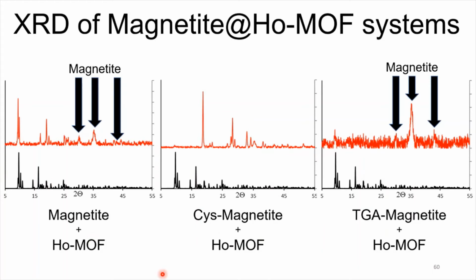Now, in the case of cysteine, it's a work in progress. We're still not sure what happened, but it is magnetic, so it might just have changed the nature of the MOF synthesis conditions and the product. But overall, even though this looks very noisy, this is mostly what you want because you can still see the peaks of the MOF in there. They're just very small compared to the magnetite, which means your coating around the magnetite is really thin. And this is something that you want because you need smaller particles to be able to inject them.